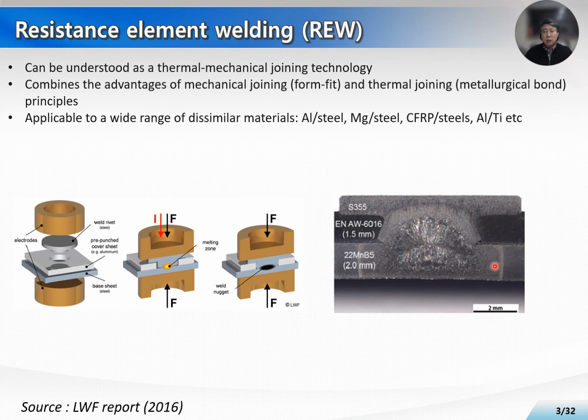Here, aluminum of 1.5 millimeter thickness has been joined with hot stamped steels using an element with resistance heating. The very large nugget diameter secures the bond strength between element and steels. At the same time, the element head is pressing down the aluminum plates, which works as an interlocking mechanism for joint strength.